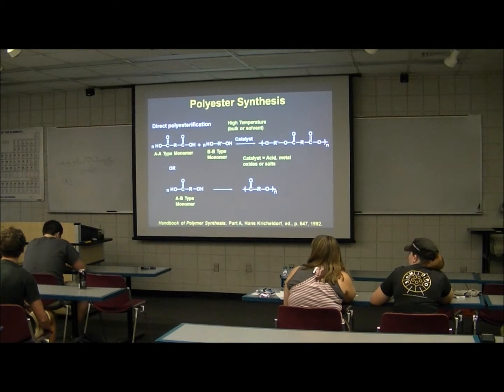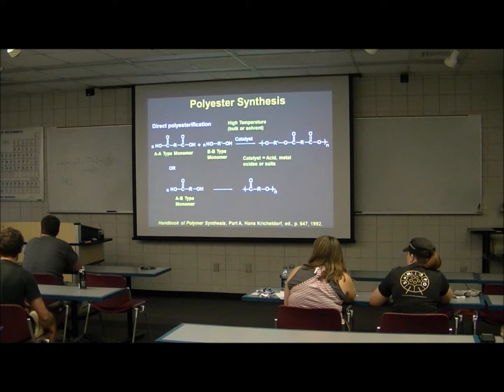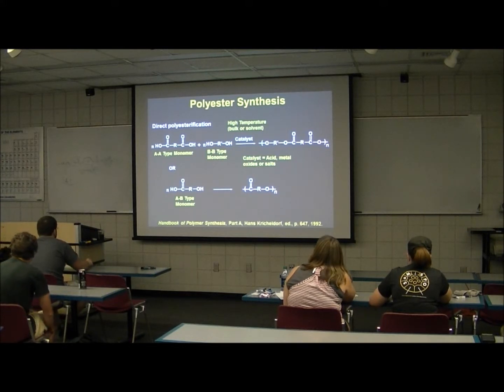And as we start the synthesis, it's all hazy, it's turbid. We haven't intentionally added water, but there is some water in there. And then we warm it up and we see some water come off and we think we're making progress and it's still turbid. And then all of a sudden, at some degree of conversion, probably right around 35 to 50%, the entire reaction will go clear. And it goes clear because we finally made enough dimer so that the acid that's not soluble in the rest of the mix becomes soluble in all of it through a homogenization process, or a compatibilization process.